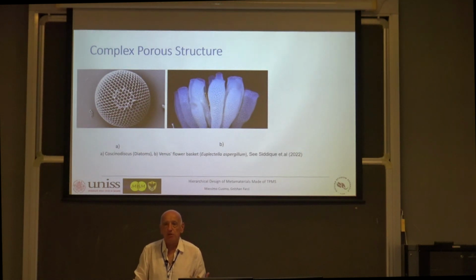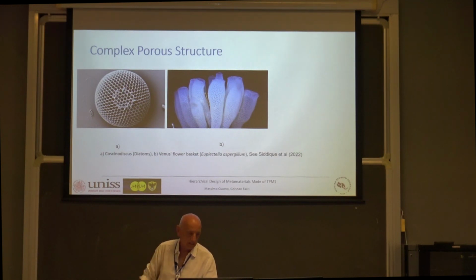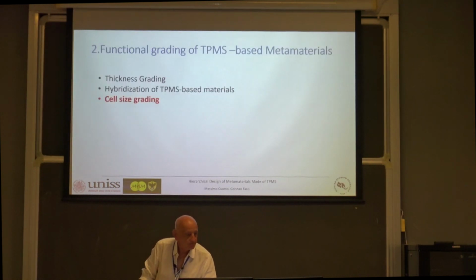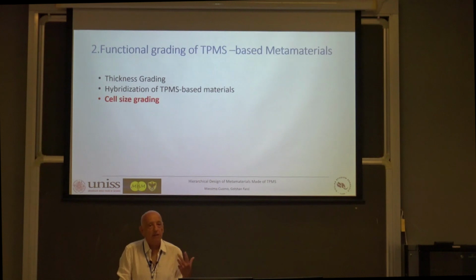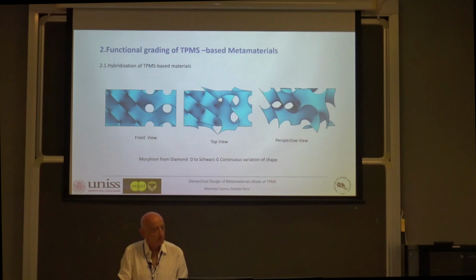An additional thing we find in nature is that these structures are usually not homogeneous, so they are combined in a hierarchical way, even with multi-level hierarchy. There are three ways we can grade these metamaterials: we can grade the thickness, we can hybridize the structure, and we can change the cell. So this is hybridization. We start from, what is this, a diamond, and we go to a gyroid. This is a continuous transition.